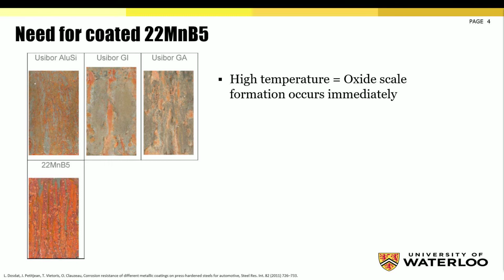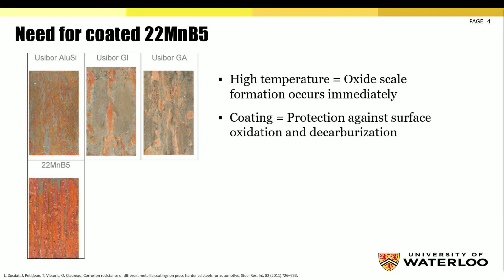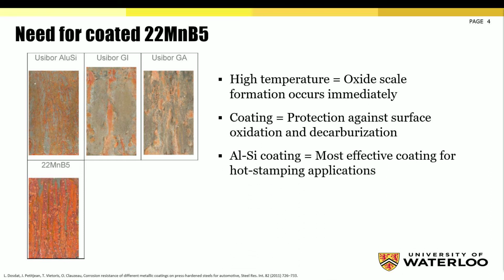Now, as with most steels, surface oxidation is a significant problem for 22 Mn B5 steel, as oxide scale formation occurs immediately at the elevated hot stamping temperatures. So the use of a coating to protect the steel helps to avoid surface oxidation and decarburization, and it has been shown that the aluminum silicon coating is the most effective coating for hot stamping applications.